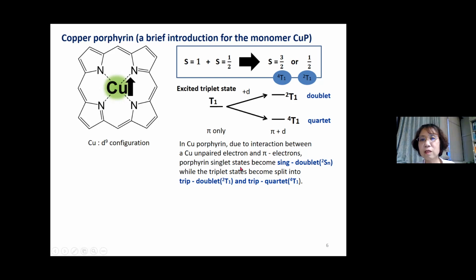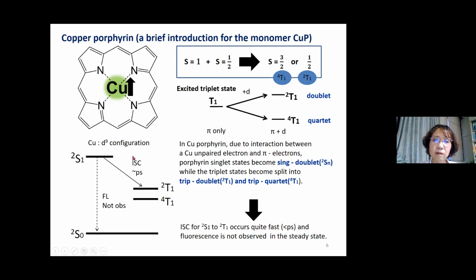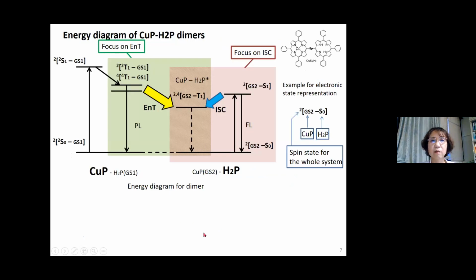And also the porphyrin singlet state becomes the singlet doublet state. Then intersystem crossing from the singlet to the triplet, exactly speaking from the singlet doublet state to the triplet doublet state, is quite fast. It is less than a picosecond, and the fluorescence from the singlet doublet state is not observed, and we can observe phosphorescence from the equilibrium state of the triplet doublet and triplet quartet states. So here is a detailed energy diagram of the copper porphyrin, free base porphyrin dimers. If we excite copper porphyrin,